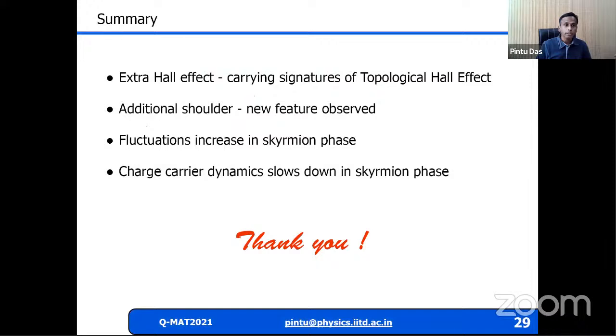So with this, I would like to summarize. We have observed an extra Hall effect, which carries all the signatures of the topological Hall effect that people have reported in the literature so far. We are also seeing an additional shoulder, which is a new feature that has not been reported and which is very much reproducible in our system.